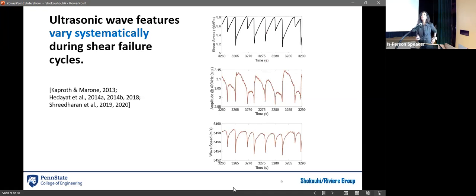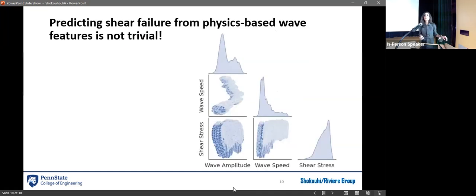Putting this all together, on the top is shear stress versus time. Let's look at how the amplitude and wave speed change with shear stress. Good news is, if you look at these data, and other people have done that too, you see a systematic change. It looks like our features are following shear stress. That means there are some physical reasons to believe that if you input these features, you can predict shear stress. So we are not just shooting in the dark with the data.